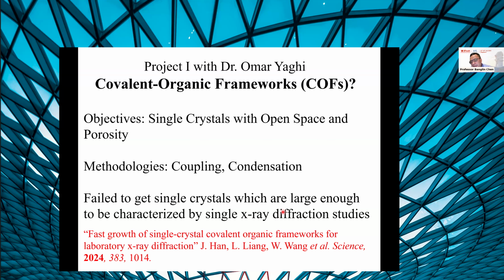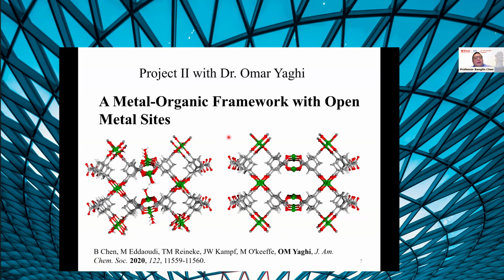Fortunately, Dr. Yaghi also allowed me to develop a second project, which I was more comfortable with, metal organic frameworks. So I will show you two works from his lab. One is where I used this adamantane tetracarboxylate as a linker with copper paddlewheel, and the structure, of course, is predictable. It's a platinum sulfide structure. The most important thing is that once we remove all these terminal water molecules, the crystal is still stable, and all the terminal water molecules can be removed, giving what we call the open metal site.